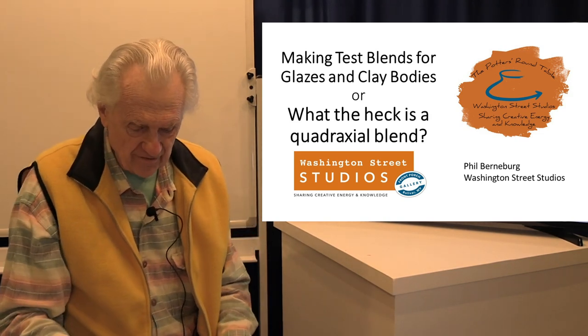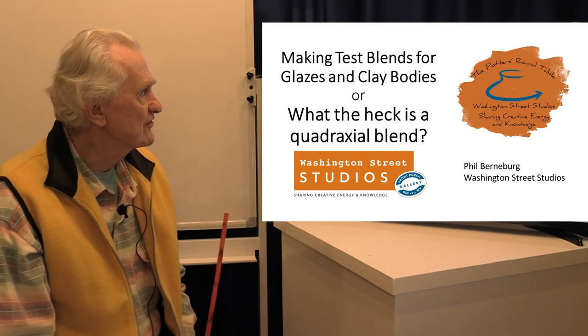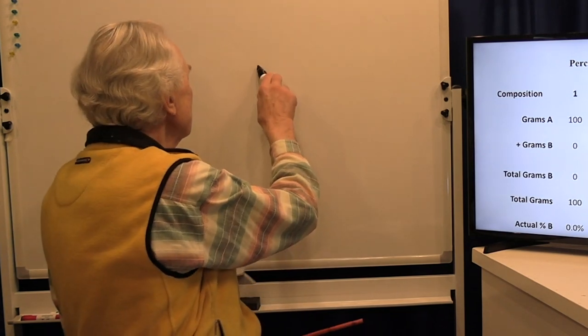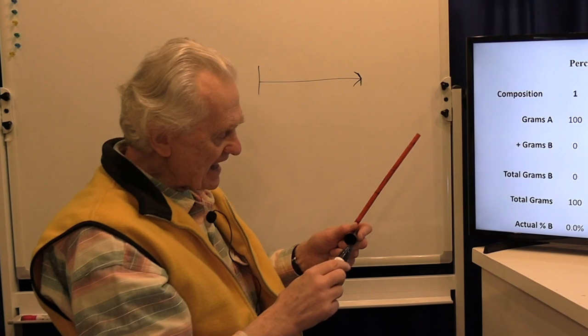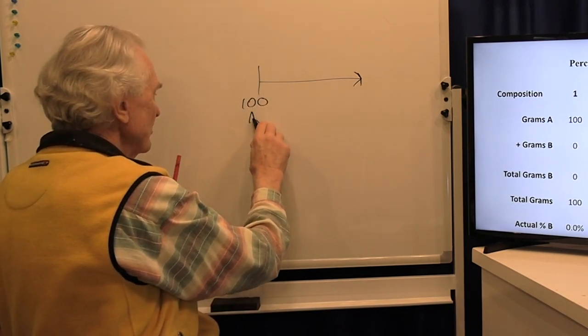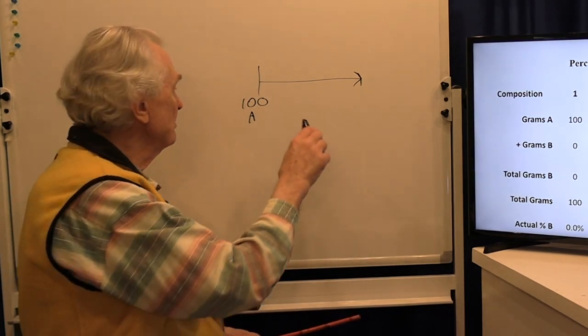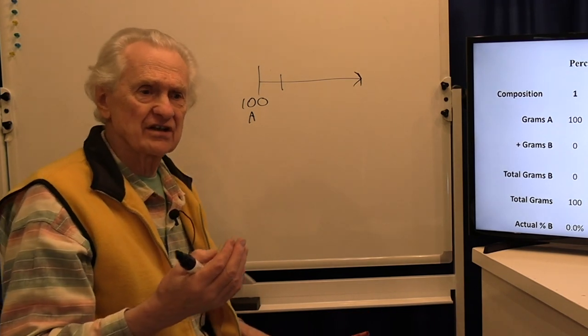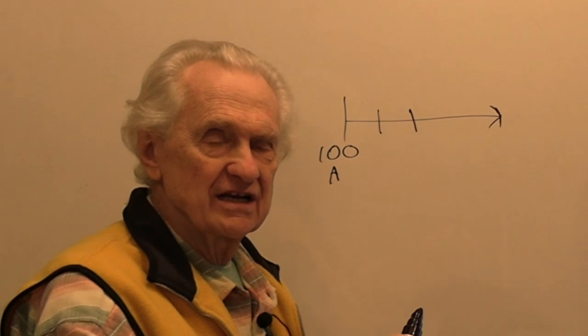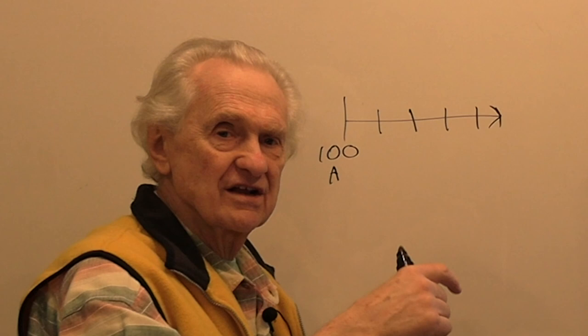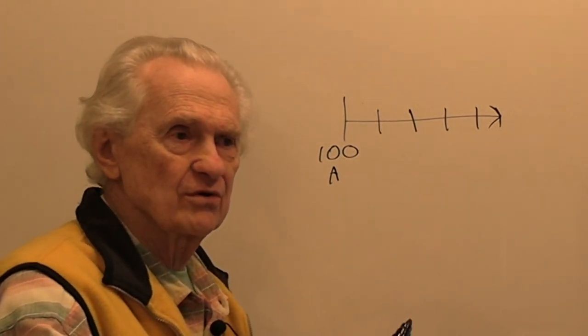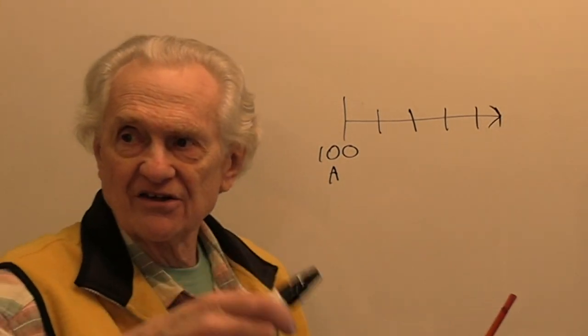Starting with two ingredients, there are two approaches, and they're called line blends. The first is called an additive line blend. You take 100% of ingredient A and add a small amount of B. You take a sample, then add another portion of B, mix it up, and dip another sample — and keep doing that. Every time you make an addition, you take another sample. So you're not making separate batches; you're changing the composition of one batch as you go along and taking samples throughout.